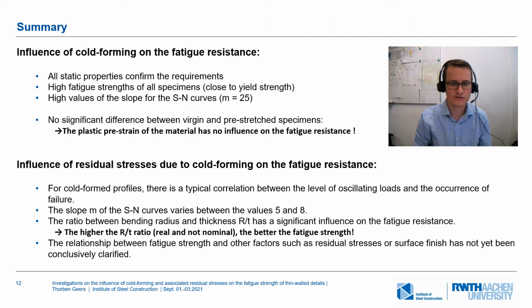Finally, a summary of the results is shown. First of all, the tested material meets all static requirements. The fatigue strength of the virgin and pre-stretched material showed high values in the range of the nominal yield point. The slope of the SN curves is about 25. A difference between the two main orientations and between virgin and pre-stretched material could not be determined. An influence of the cold forming on the fatigue strength can thus be excluded.